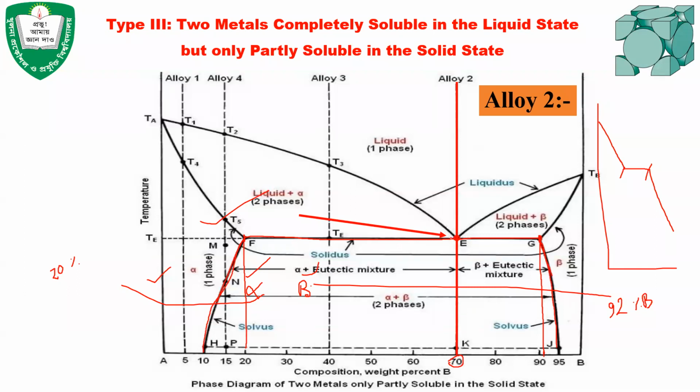It will be like in this case the 100% eutectic mixture. It is a two-phase region, alpha and beta. It will be the same, but the problem is that the chemical composition of alpha and the chemical composition of beta changes when the temperature drops.